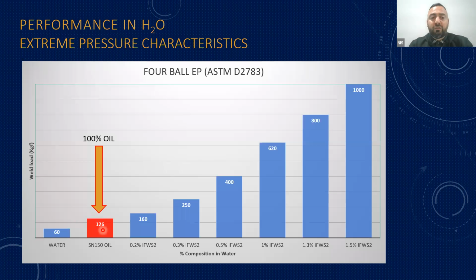It ruptures the film at 126 kilogram. Now you're adding 99.8% of water and 0.2% of particles. You're already surpassing the 100% oil. So 99.8 water, 0.2 particles, one load stage higher than oil, 100%. And you just keep adding.